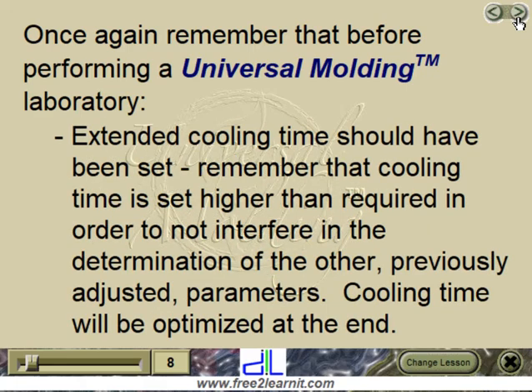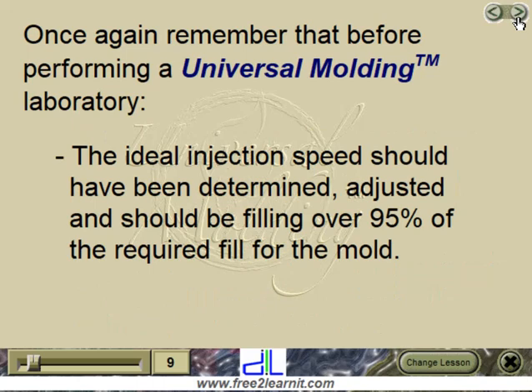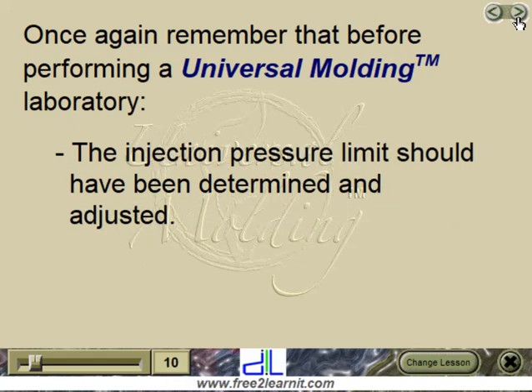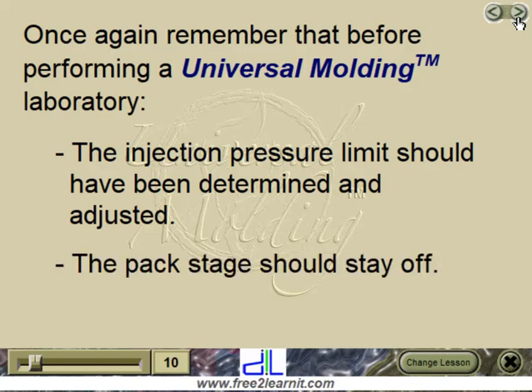Extended cooling time should have been set. Remember that cooling time is set higher than required in order not to interfere in the determination of the other previously adjusted parameters. Cooling time will be optimized at the end. The ideal injection speed should have been determined, adjusted, and should be filling over 95% of the required fill for the mold. The injection pressure limit should have been determined and adjusted. The pack stage should stay off.